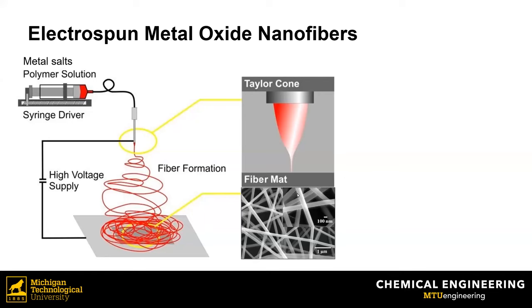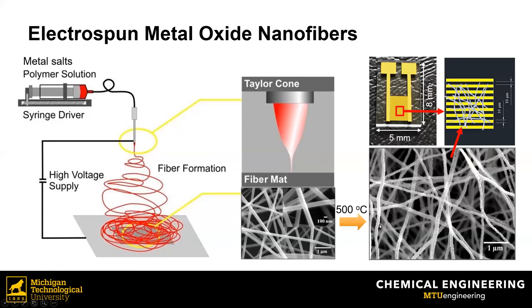So what you just saw was the polymeric nanofibers we collected on the foil. After that, we put them into a furnace to burn off all the polymers. We initially have the polymer that's necessary for generating the nanofibers, and then we burn it off. It's kind of like a sacrificial template. Now what you see here in this larger SEM image is the metal oxides. All the metal ions turn to metal oxides. Then we deposit those metal oxide nanofibers on the electrodes to bridge the interdigital electrodes and evaluate the sensing performance towards different gases.